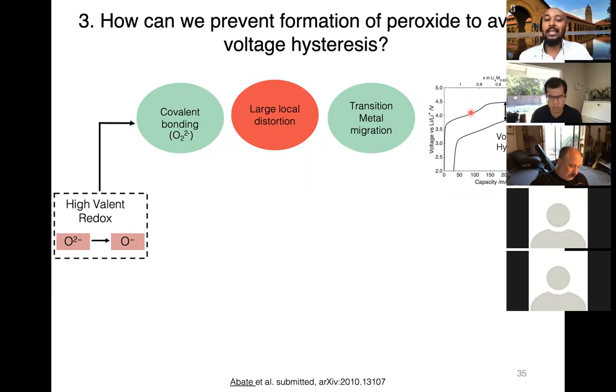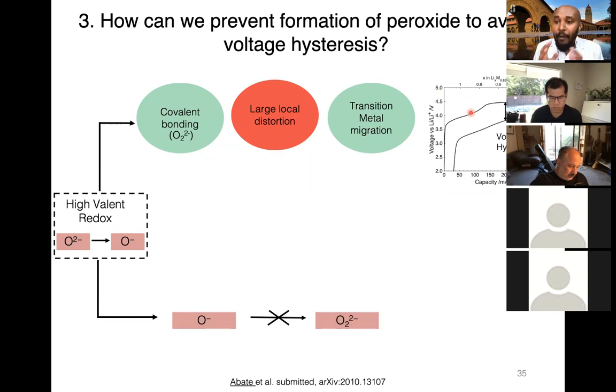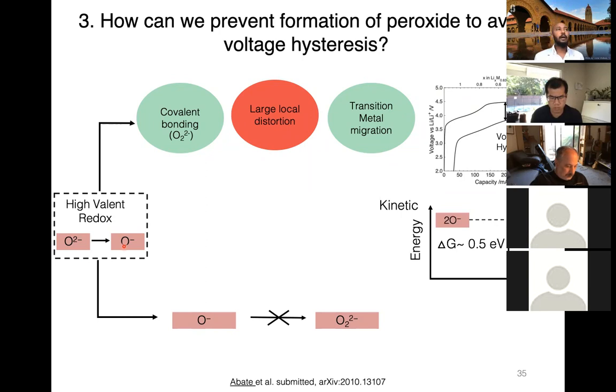But the question I would like to ask is, can we actually prevent this pathway? Thereby, we can prevent the formation of covalent bonding while we stabilize the O- species as they are, without having this local distortion and cationic disorder. One can think of addressing this problem in two different ways. The first is to design a material that has a large kinetic barrier for the O- species to form a peroxide. Therefore, in typical cycling conditions, we won't observe this peroxide formation and the O- are stable as they are because of the kinetic barrier.